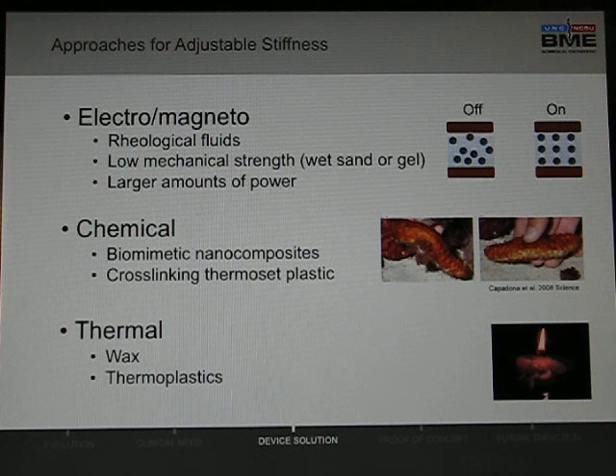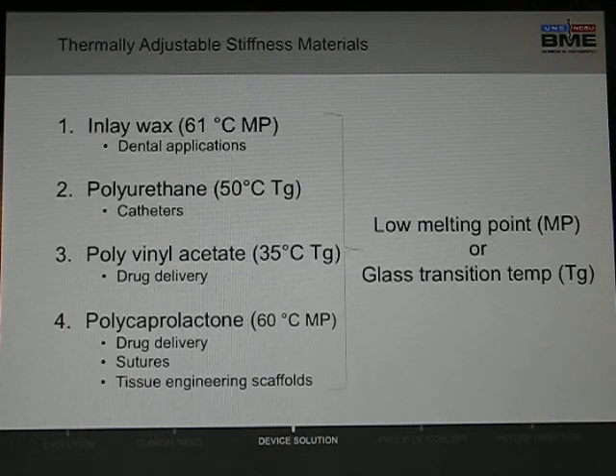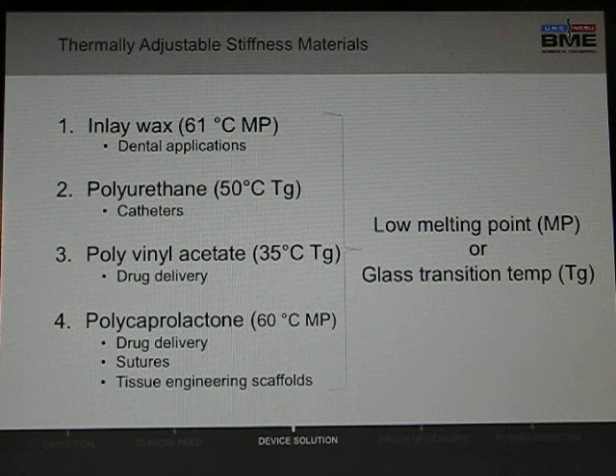You can also thermally induce stiffness change by melting and solidifying of wax and thermoplastics. We decided to choose the thermal approach because it was easy, and with thermoplastics the process may be reversible. Here's a laundry list of thermoplastics, in this case biocompatible polymers, all having low melting point or glass transition temperatures. The low temperature requirement was important because this material would be used in an interventional device, therefore we wanted to prevent thermal damage to the surroundings.